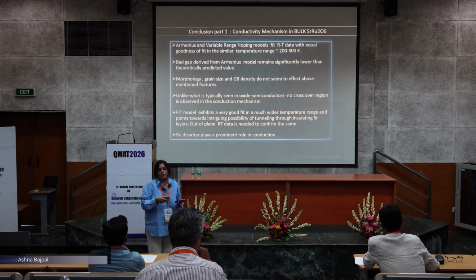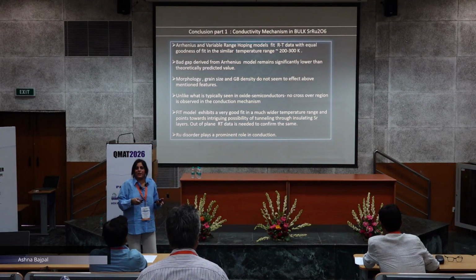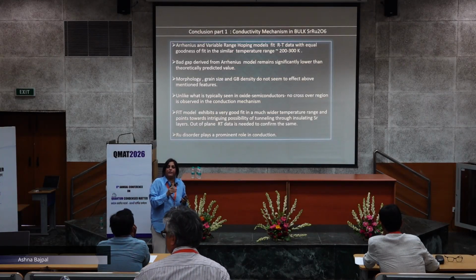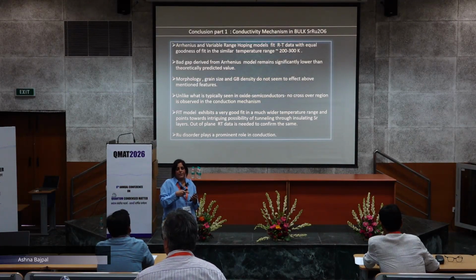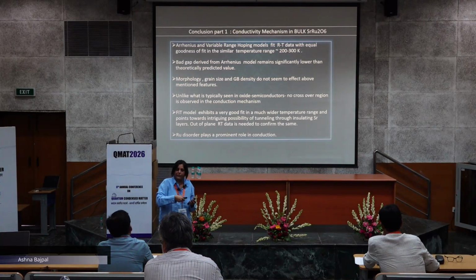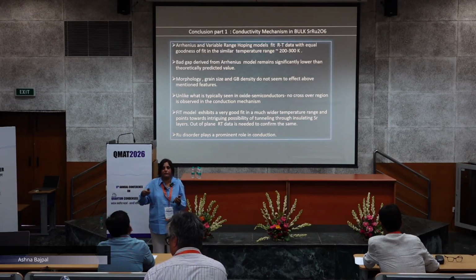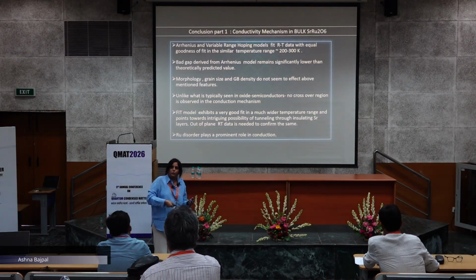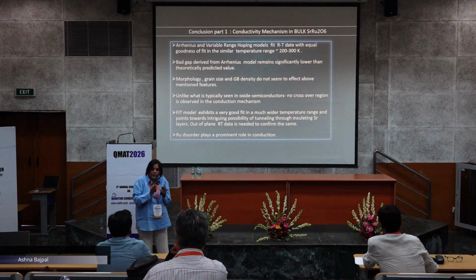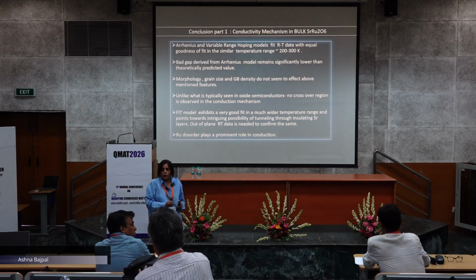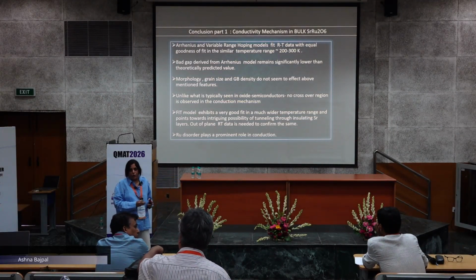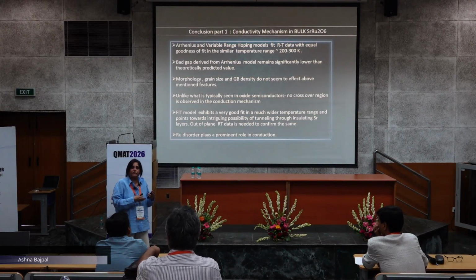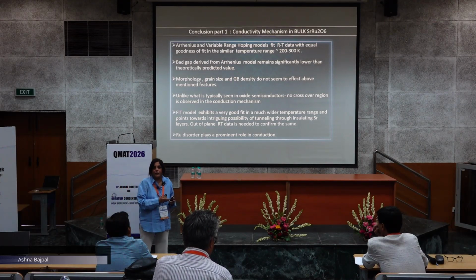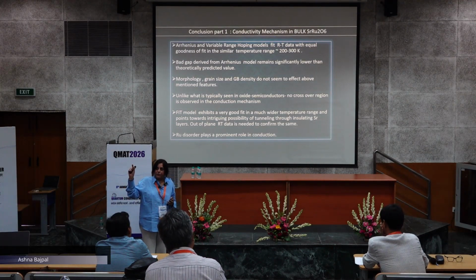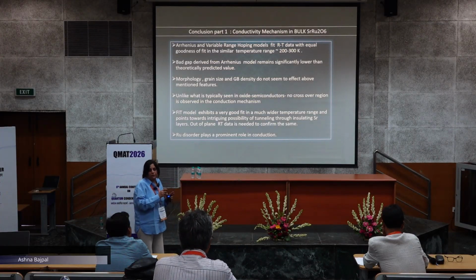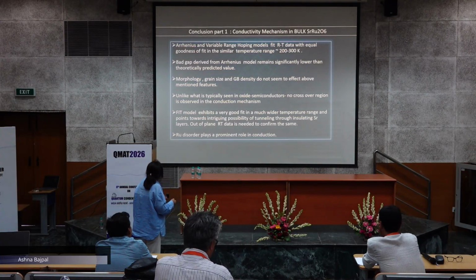I won't bore you with all the gory details, but it appears to us that below 50 Kelvin it has to do with antiferromagnetic correlations and all the things which are touted for this system, like both localized and itinerant character of electrons, which gives you this benzene-ring-like conduction where the electron can be localized within one Ru hexagon, or it can travel also. So below 50 Kelvin, where even FIT does not seem to fit, Ru disorder seems to play a very prominent role, and we need magnetoresistance measurements to understand the effect of antiferromagnetic correlations on the transport. That is still remaining, but at least we have come from an understanding between 200 to 300 Kelvin down to 50 Kelvin, where we think fluctuation induced tunneling seems a very plausible model.